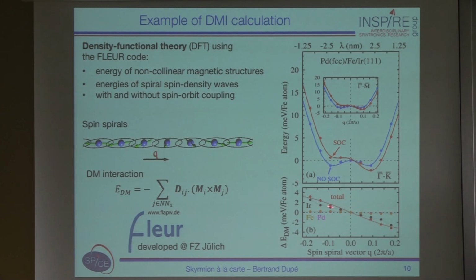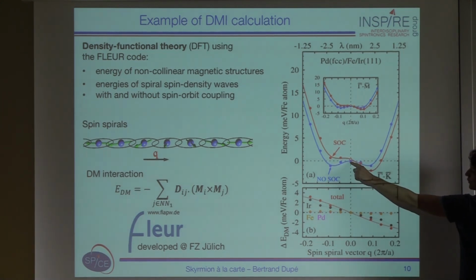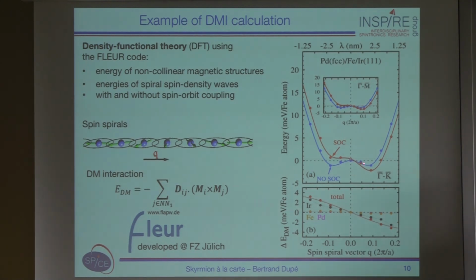So now if you take this curve, you can map it here into this Hamiltonian, which is the Dzyaloshinskii-Moriya Hamiltonian, which has here the Dzyaloshinskii-Moriya vector. So now what you can see on top of that, so that's the chiral contribution to the SOC. There is a very small other contribution which is shown here. So here the blue point is being lifted up to the red point here, and that corresponds to the magnetocrystalline anisotropy.